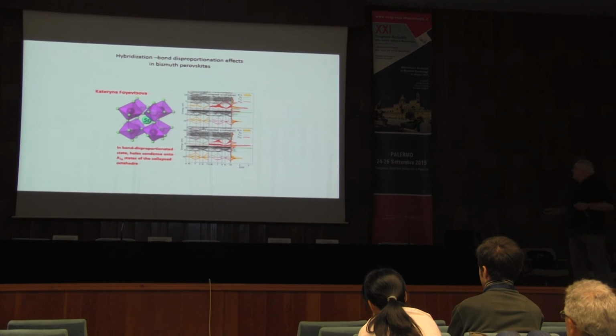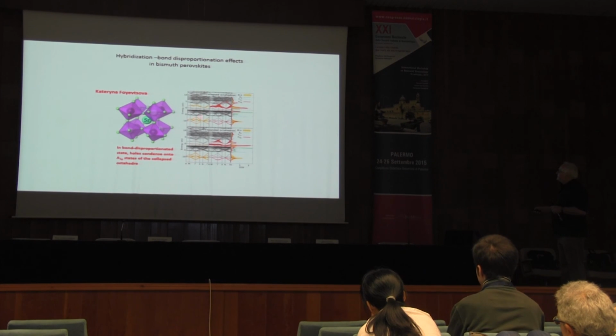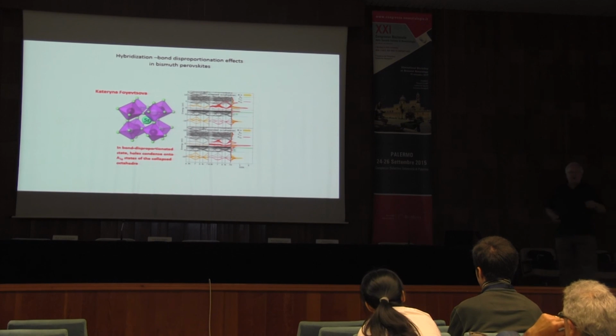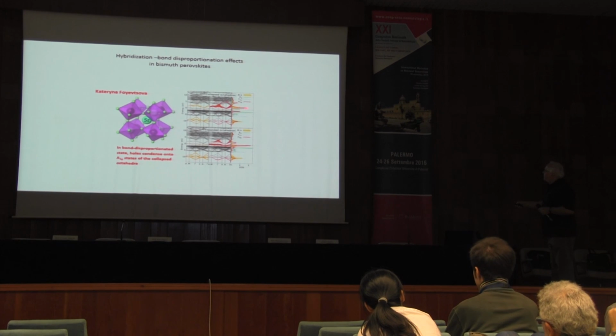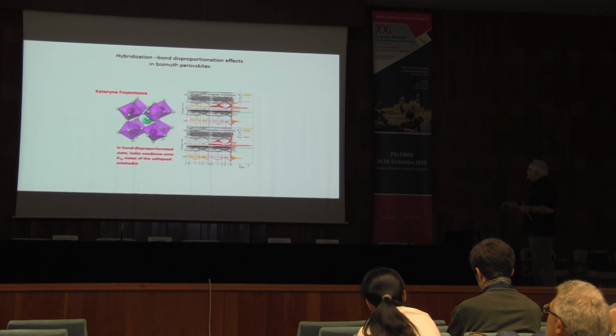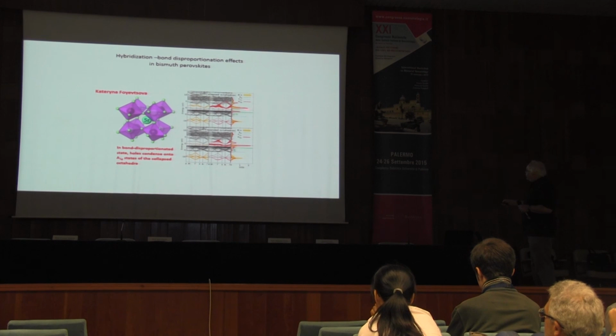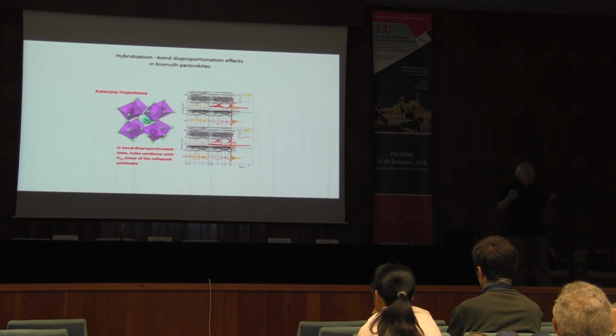Well, actually, this is already the band structure calculation. We shouldn't have much of a problem of correlation. But the 6s band is here at minus 10 electron volts. It's got piles of dispersion. But actually, all of that dispersion comes because of the hybridization with oxygen, and not because of bismuth-bismuth mixing. And these states that were down at the bottom, the A1g states in oxygen that were at the bottom of the oxygen band, zoop, get pushed up above the Fermi energy, and there are your holes. These are oxygen holes of linear combinations of A1g symmetry, which get pushed up over there because of strong hybridization, and the 6s of bismuth gets pushed down over here. And notice how narrow that band is. It suddenly has become a very narrow band, actually.